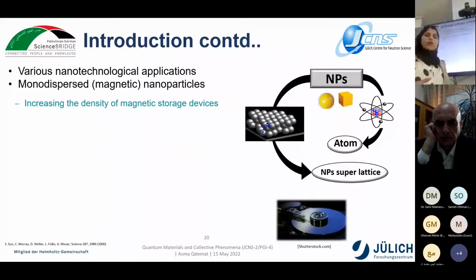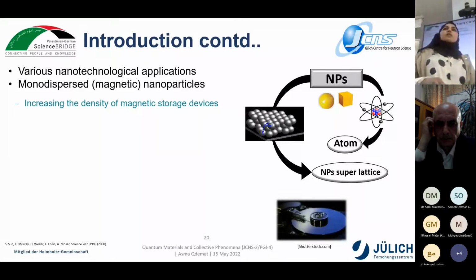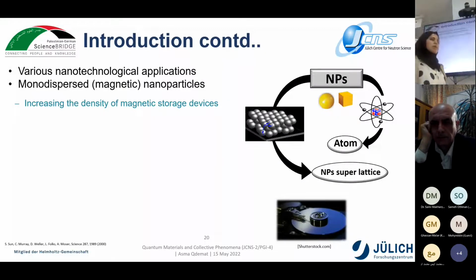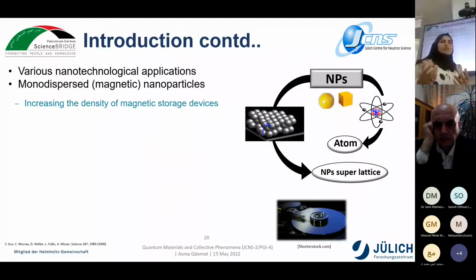Besides this, the magnetic interaction between nanoparticles is still not well known, and it is becoming an important parameter that we need to understand and control. The magnetic interaction between atoms in bulk is well known, direct and indirect exchange coupling, but it is not known between nanoparticles. To my knowledge, this magnetic interaction has only been studied using macroscopic magnetization techniques, and only for particle assemblies showing short range order.